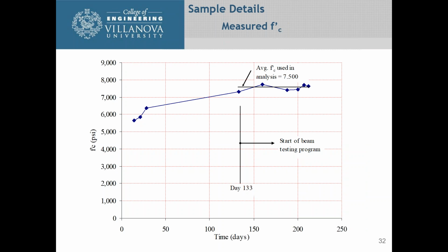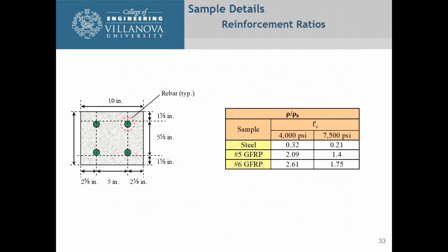Well, as you know, concrete usually comes in a lot higher than what you specified, and in this one, it was 133 days before we started doing any testing, and by that time we took concrete cylinders and found that our strength was actually more in the range of 7,500 psi. So with that, we had to go back and take a look at our reinforcing ratios and make sure that we are still okay. So you can see on the table on the right, based on 4,000 psi concrete, what our reinforcing ratios were, and they were in the order of magnitude of 2 with 4,000. By going to 7,500, they were around 1.5. We're still greater than 1, so therefore the premise that we're going with, that the concrete is going to fail first before the GFRP bar does, was still holding true.